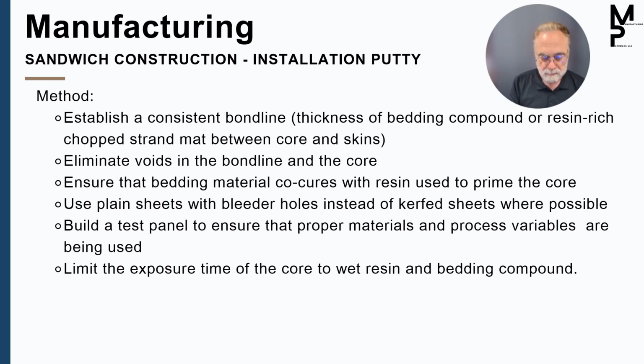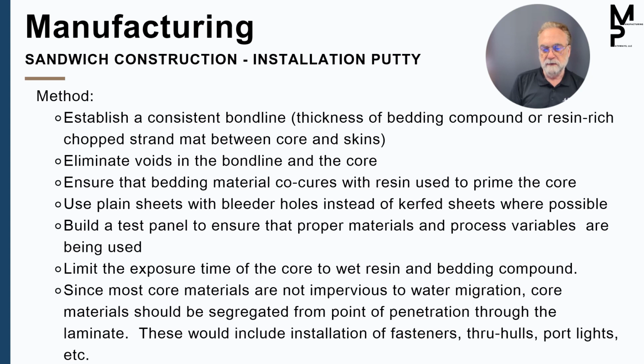If you're wet bagging, or sorry, if you're using a chop mat core bedding, all right, you also, depending on the core, may want to limit the amount of time that the resin is exposed to the core material. So some of the cores can get softened by the resin. So if you're doing a very long infusion, for example, and you have a 2 or 3 or 5 hour gel time, you might want to run a test first just to make sure that the core material is stable for that long as the resin cures.